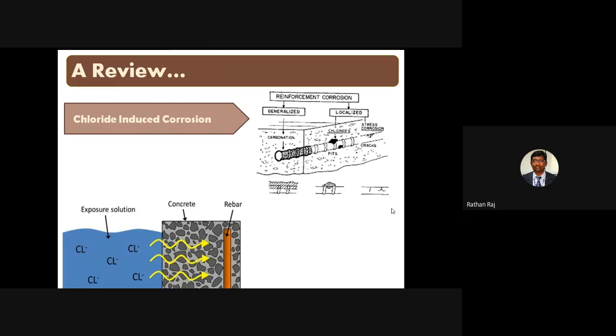So when we talk about the next corrosion, corrosion due to carbonation, this corrosion is called generalized corrosion. In concrete, when the concrete gets attacked by carbonation to the level of the steel rebar, the normally alkaline environment which protects steel from corrosion is replaced by a more neutral environment. Under these conditions, the steel is not passive and rapid corrosion begins.